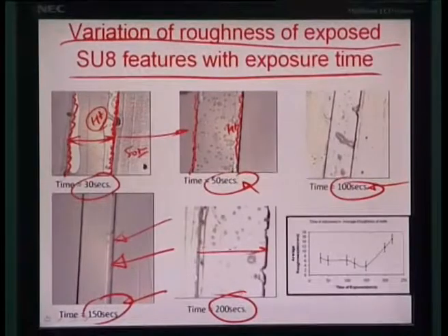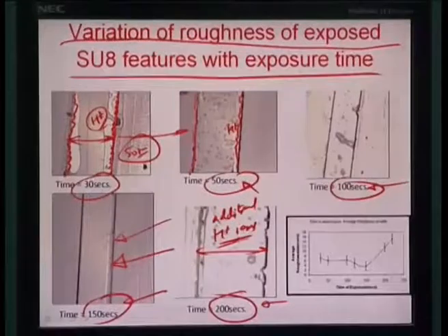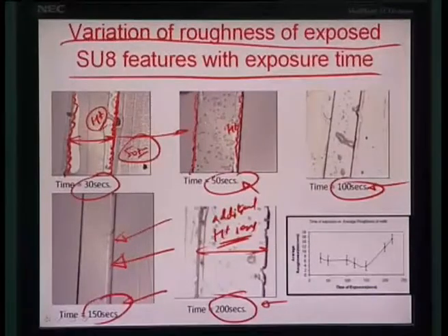So, this in fact is much bigger at 200 seconds, much bigger than at 150 seconds, which is actually equal to about 50 microns. This may be bigger on account of the fact that additional H plus ions are generated here because you have overexposed the resist material, and so the additional ions would diffuse and create a very rough edge in the positive direction.